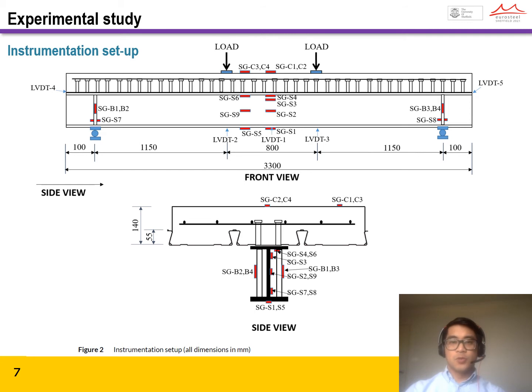Instrumentation setup is shown in this figure. The composite beams were tested under four-point bending. The clear span of all beams was 3.1 meters, and the pure bending region between the two loading points was 0.8 meters. Three LVDTs were placed at the midspan and two loading points to measure displacement. LVDT 4 and 5 were placed at the interface between the high-strength steel beam and slab at both ends to measure slip. Nine strain gauges were installed along the height of the high-strength steel section and four at the concrete surface. These were to measure the strain history distributed in the composite beam cross-section.